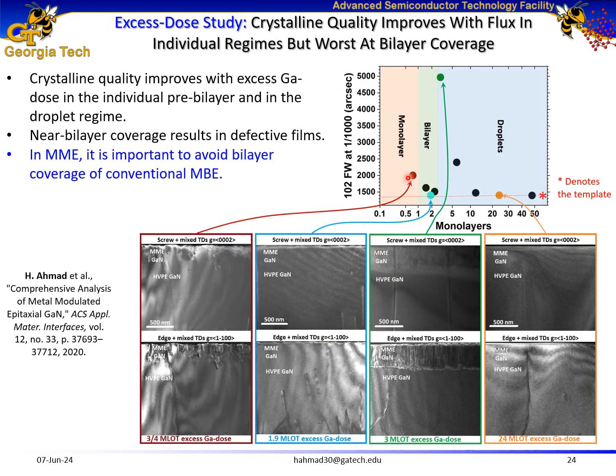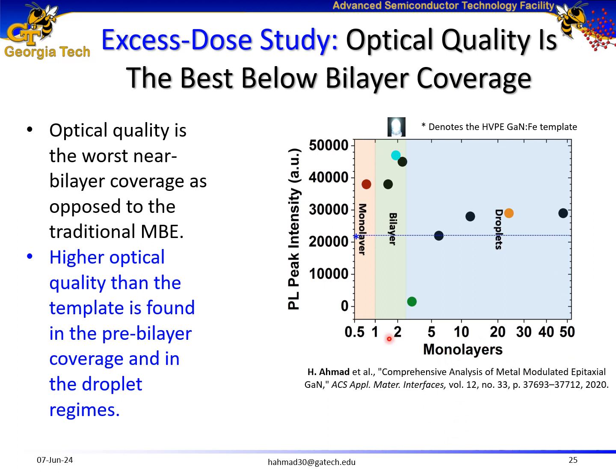Also, from X-ray measurements and validated by transmission electron microscopy measurements, we found a trend of improvement in crystal quality with excess gallium dose in the individual pre-bilayer coverage regime and also in the droplets regime. However, film quality was found to be the worst near bilayer coverage, which is totally opposite result as compared to the traditional MBE. And we also found from optical measurements that the optical quality is the worst near bilayer coverage, but for the remaining growth conditions, the optical quality was even better as compared to the template.